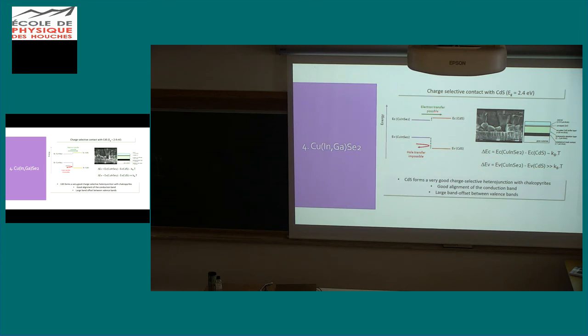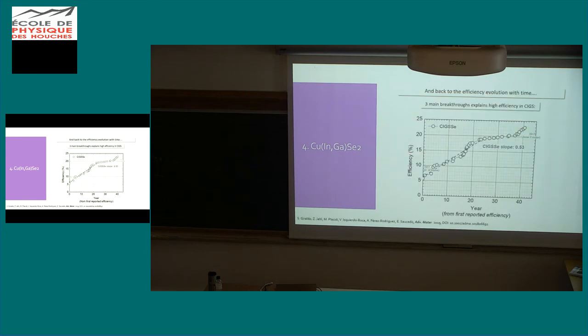Also, CIGS uses cadmium sulfide as selective contact for electrons because in particular with copper indium diselenide, the band alignment is perfect. It's very good for electron transfer and really blocks holes in this heterojunction. So it's the perfect partner that almost everyone is using, although some groups and one of the companies, Solar Frontier, have developed cadmium-free buffer layers that work as well as cadmium sulfide. But normally all the people use cadmium sulfide.